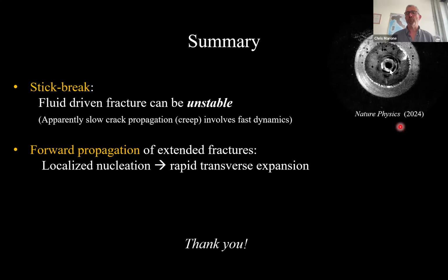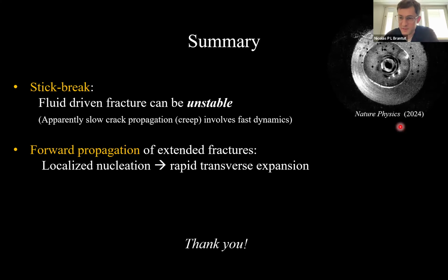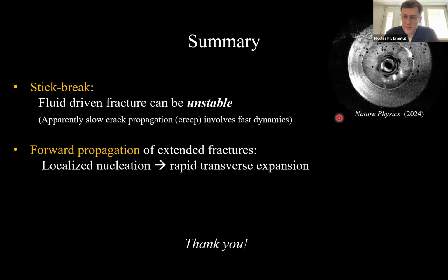Nick: Hello, great talk. Thanks a lot. These experiments remind me of what people have done when looking at stress corrosion cracking in minerals and crystals, and even single crystals. When you use stress corrosion cracking, the average crack propagation rates are very, very slow, like 10⁻⁹ meters per second, but you still get acoustic emission. And the acoustic emission rate is proportional to the crack growth rate on average. So do you think there's something at play that could be similar here, or should we look at something else?